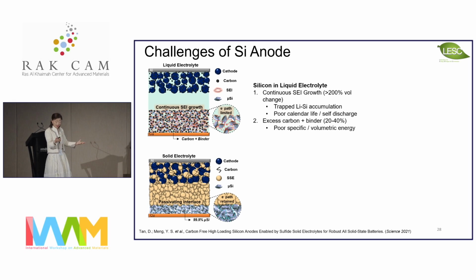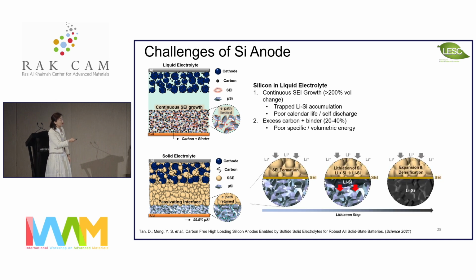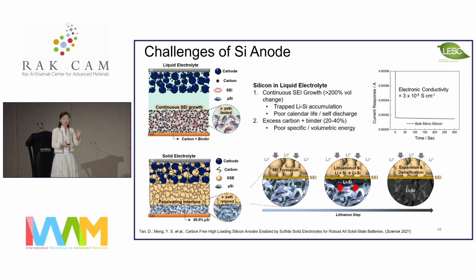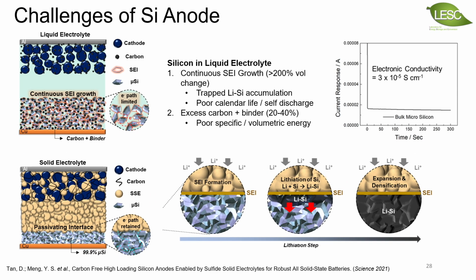So if the silicon takes lithium, it's going to volume expand. Why don't we let it expand? But because the electrolyte cannot flow down, you will have a solid-state lithium-silicon alloy reaction without any interference from the electrolytes. And he's right, because when we use the cheapest possible silicon, actually we can use silicon recycled from the amorphous silicon solar cells, and you can alloy this silicon with lithium at a very fast rate, and you make a functional solid-state battery with pure silicon, very cheap, no nanostructure, just very, very low-cost silicon.